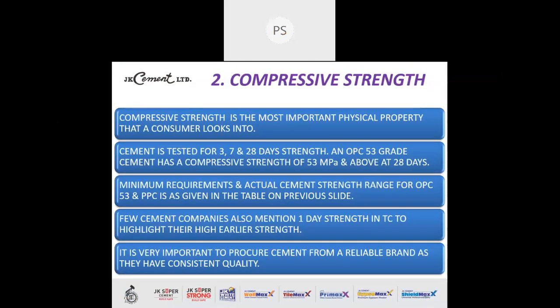Now, the compressive strength is the most important physical property that a consumer looks into. As a quality control engineer, you would definitely want that the design strength should be achieved anyhow. So that is why it is the most important parameter. Second point, cement is tested for 3, 7 and 28 day strength, and OPC 53 grade cement has a compressive strength of 53 MPa and above at 28 days. Minimum requirement and actual cement strength range for OPC and PPC are as given in the table on the previous slide.